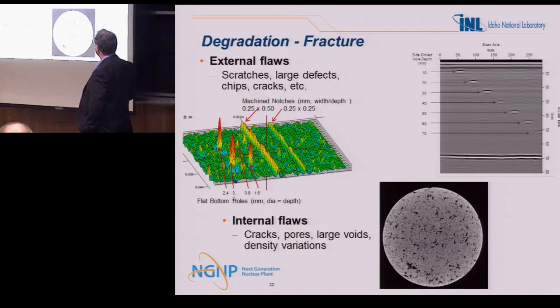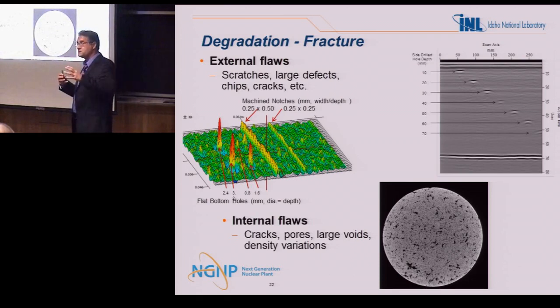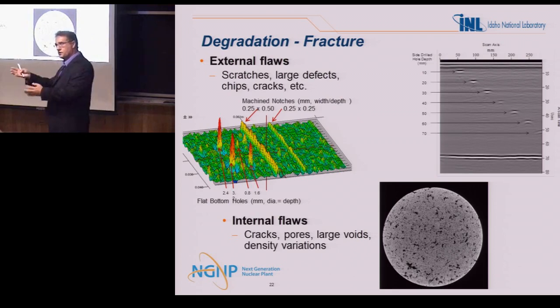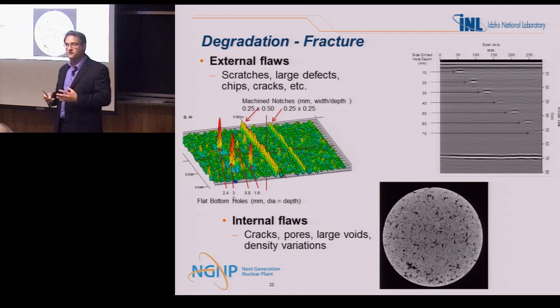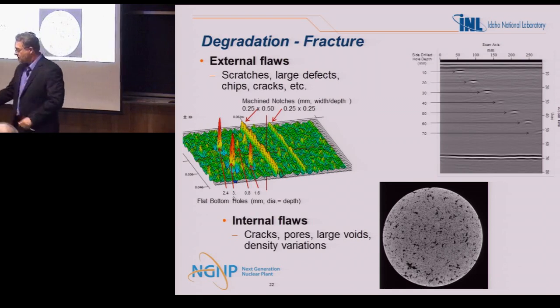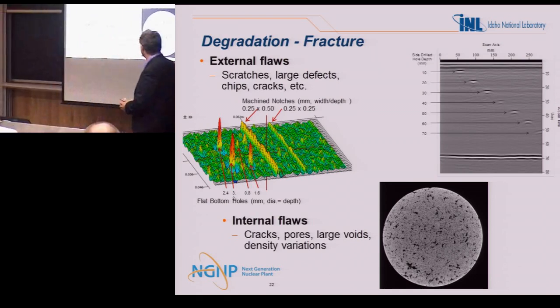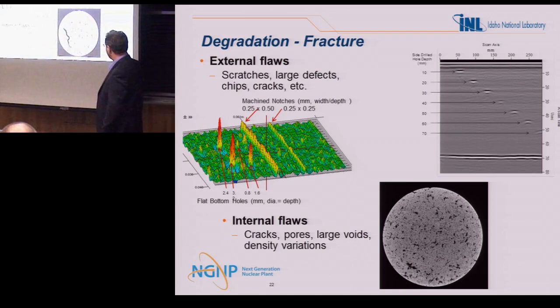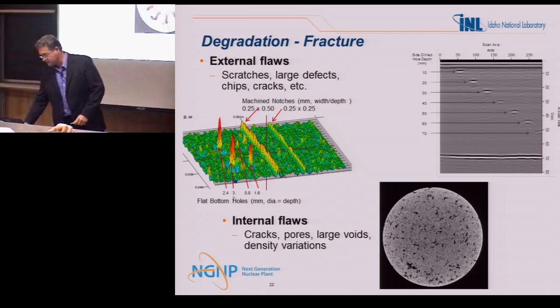Fracture, we're looking at scratches, large defects, chips, cracks. University of Minnesota has been working and trying to look at voids inside the graphite. These are engineered pieces of graphite, folks. We don't just cut them out of the ground like limestone or marble. We actually manufacture these things, and as a consequence, you can get voids, cracks, you name it inside those things. And we need to have an ability to figure out what these will do to the fracture, right? Because we don't want these things to fracture.